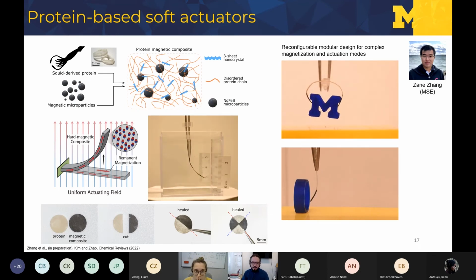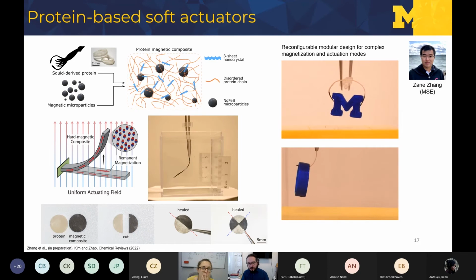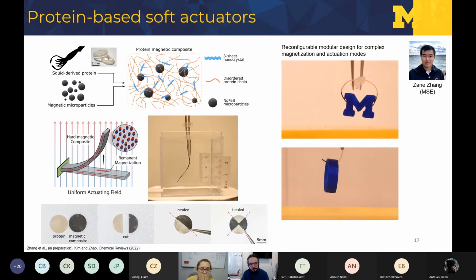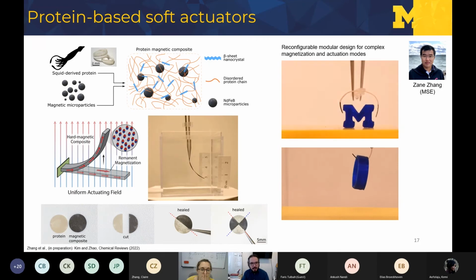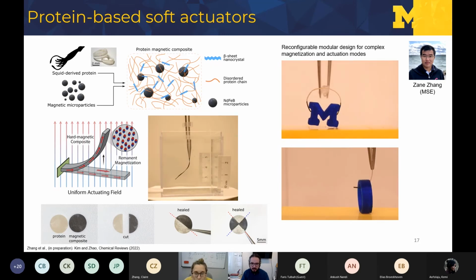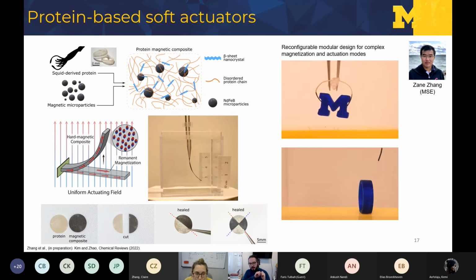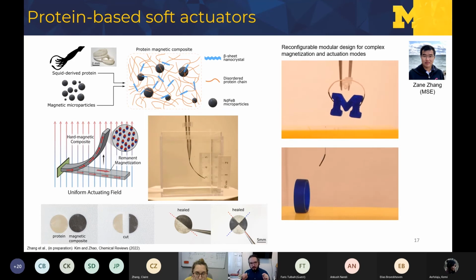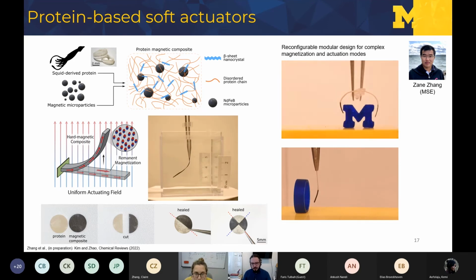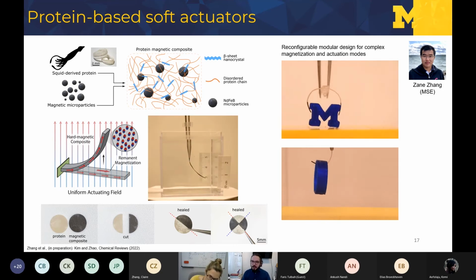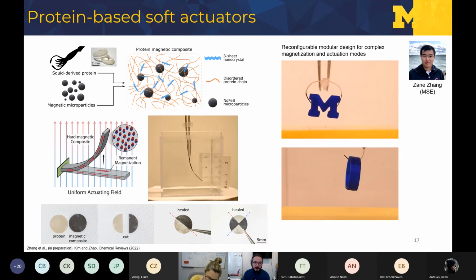And one thing that we're very interested in is applying these protein-based and bio-inspired materials to different types of actuation, right? And we're developing this very recent work from my student Zane. We're making hard magnetic composites that we can use as a smart material that can deform on demand, right? So if you can control a specific internal magnetization profile in your material by controlling the arrangement of micro and nanoparticles, when you expose it to a homogeneous external magnetic field, you will get torque-driven actuation in there, right?